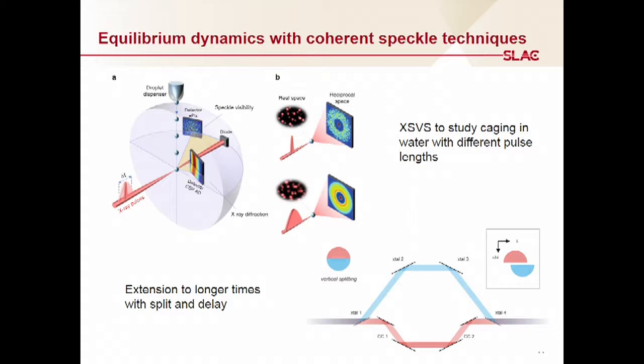One of the things they do here is look at equilibrium dynamics. Equilibrium dynamics are typically very hard to see because they are by their nature fairly small. One thing they can do with XPCS, which perhaps I should explain briefly, is take coherent speckle images of an ensemble of particles at various time delays. By looking at how the speckle evolves in time, you can get a feeling for what the dynamics are. For example, with a series of colloids, you can take speckle patterns at delta t over a long period of time and see how the diffusion works, so you can study Brownian motion.